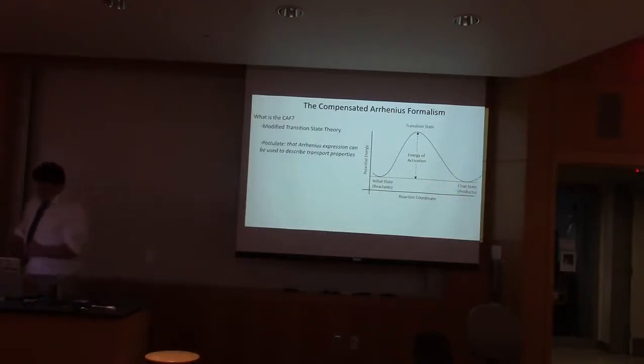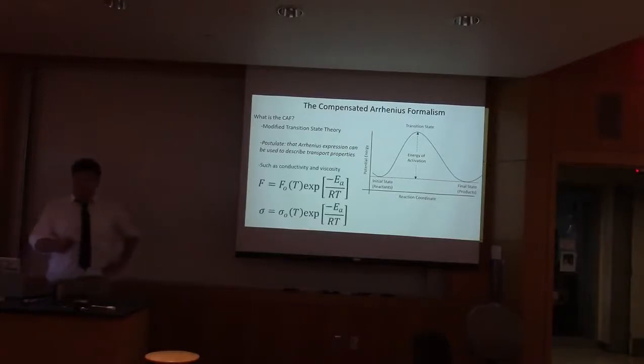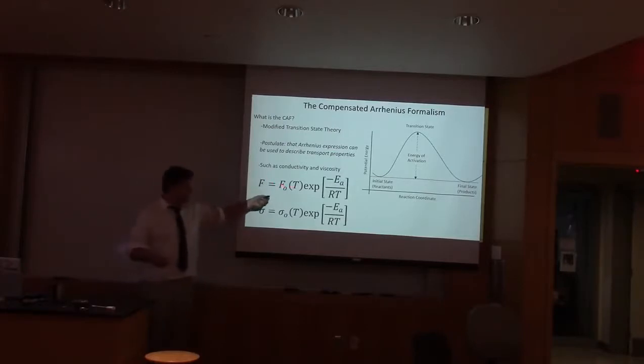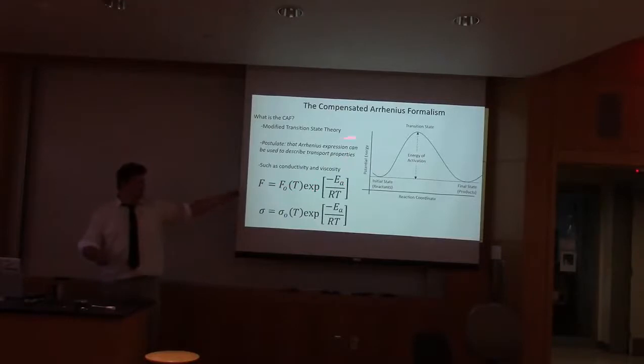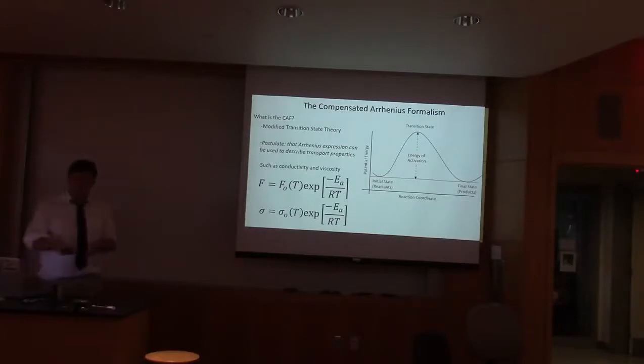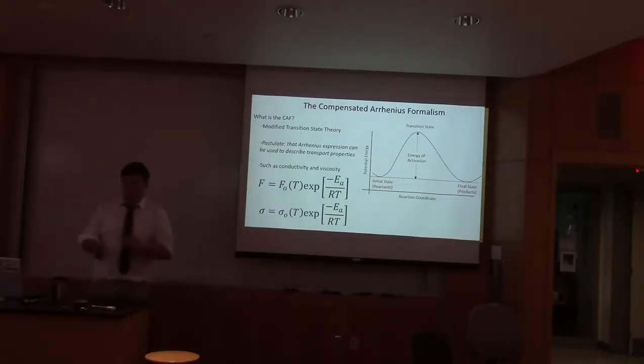Not only is the compensated Arrhenius formalism a modified transition state theory, but the first postulate of the CAF assumes that molecular transport properties such as conductivity, diffusion, and fluidity, which is the inverse of viscosity, so that's a little bit harder to keep track of, can be represented with an Arrhenius-like expression, where we have, in this case, the fluidity, the inverse of viscosity, equal to an exponential prefactor times e to the negative Ea over RT. We imagine that not only can fluidity be represented in this Arrhenius form, but also the conductivity and the diffusion.